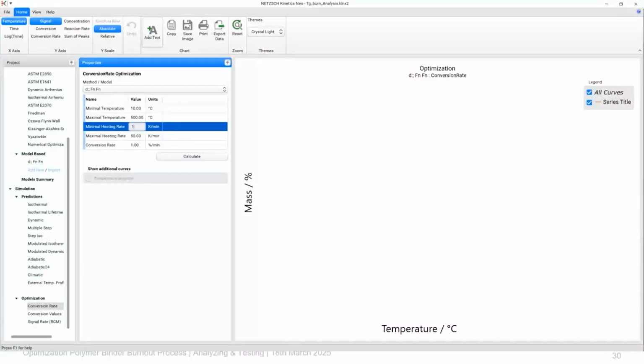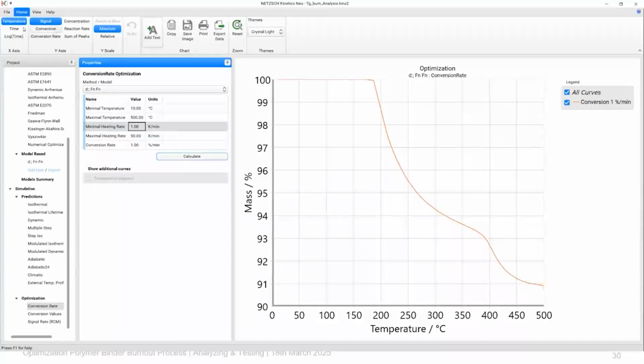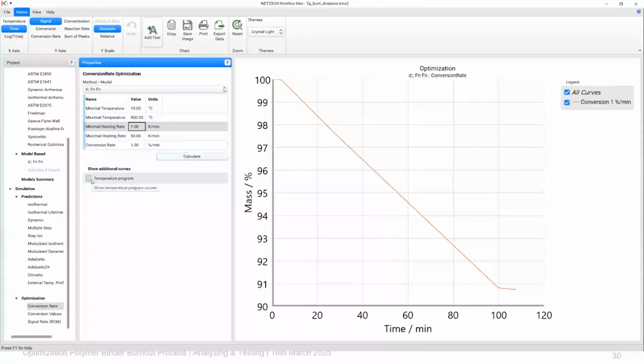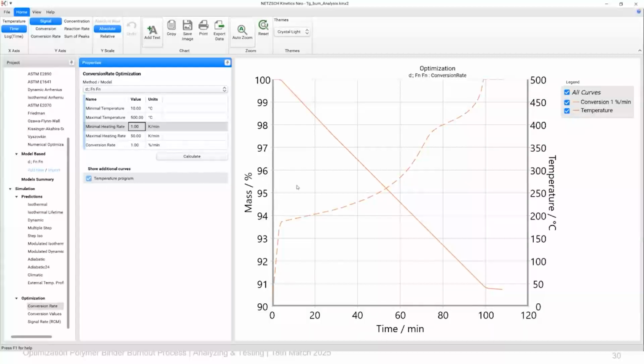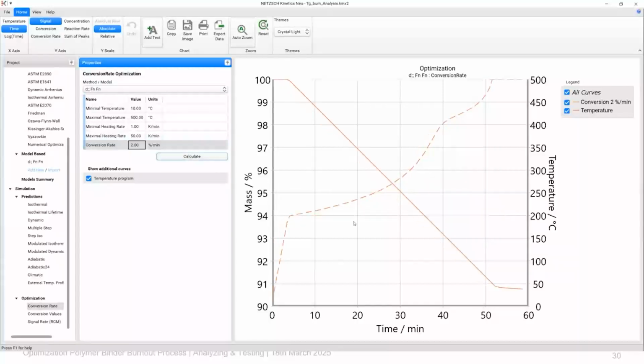I will just adjust the heating, and we can click time with the signal. And this way, we can do the optimization at conversion rate 1%. Also, if you would like, we can do 2%. In this case, we have almost 100 minutes in order to reach 1% conversion rate, or 100% conversion. If we make the conversion rate 2% per minute, and click calculation, we can see that we reach it in 55 minutes. Also, with our software we can do the prediction at different isothermal conditions.